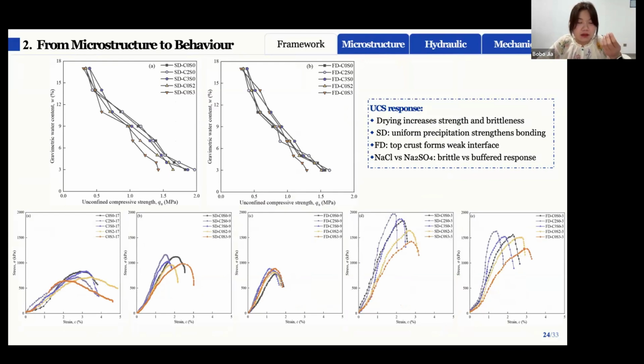Under slow drying, salt precipitates more uniformly, which enhances interparticle bonding and increases the compressive strength. However, this also leads to a sharper stress drop at failure, meaning higher brittleness. And the effects also depend on the salt type and content.